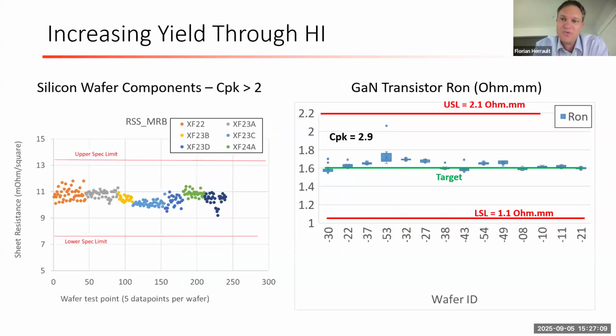One of the reasons is we can really increase yield, right? The passive yield on compound semiconductor wafers is usually one of the bottlenecks to yield high performance complex designs. With silicon, that's not the case. So I picked one of the 10 key parameters that we're tracking from our silicon supplier. This is a sheet resistance for one of the metal layers. What you're looking at is sheet resistance on the y-axis on the left-hand side, in milliohms per square, as a function of the number of wafers that we've received from our vendor. And what you can see is a very, very tight spec around the sheet resistance. This is true for all key parameters. The yield is effectively 100% through those foundries, right?